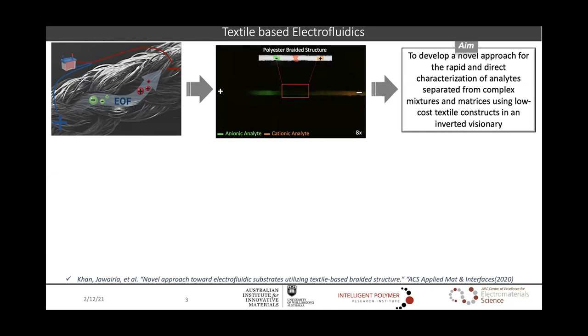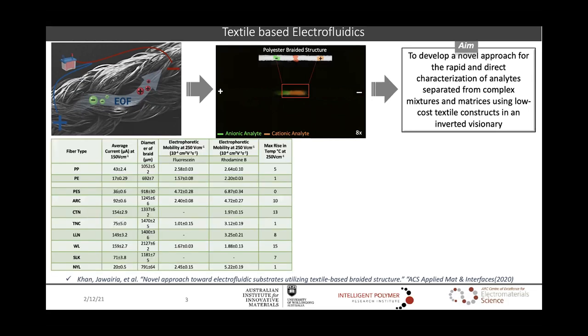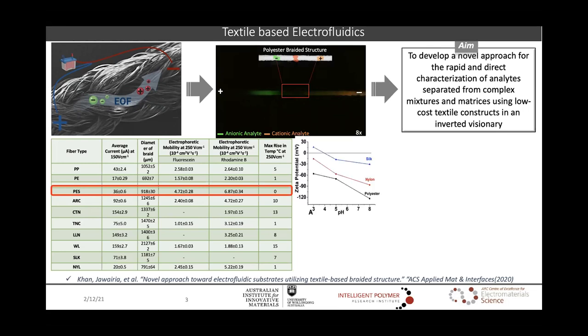So the overall aim of the project was to develop this novel approach for the rapid and direct characterization of solutes on these low-cost textile constructs in an open format, in contrast to closed glass capillaries where direct access to the sample zone during separation is nearly impossible. For this purpose, we studied the electrophoretic properties of a range of commercially available textile fibers, and we found that polyester is the most suitable fiber for fiber-based electrophoresis due to its highly negative zeta potential over a wide range of pH.